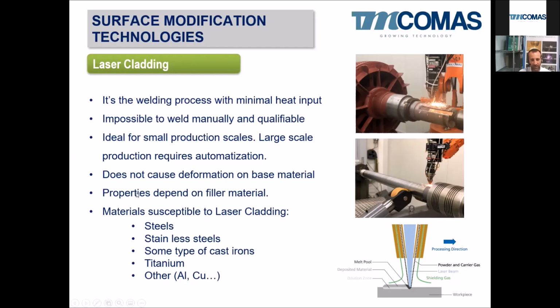The properties, like in normal welding, depend on the filler material. Here at COMAS, we are using powder. In powder, we have quite a lot of filler materials to choose from, and other people are also using wire, which also allows you to use more or less the same materials that we have in our portfolio. So we can choose different materials to make these coatings, these layers: Inconel, Stellite, tungsten carbide, duplex, titanium, martensitic stainless steel, austenitic stainless steel, and so on.